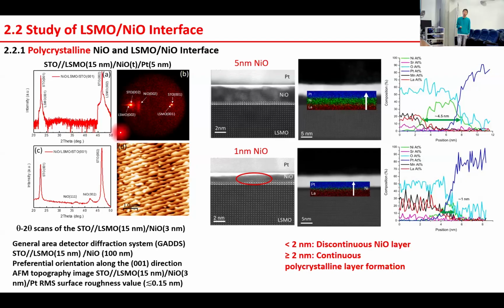With the 2D detection, we show the nickel oxide has a preferential orientation along 002. And also there's the integration curve, so there are both nickel oxide peaks, nickel oxide 111 and nickel oxide 002, indicating the polycrystalline structure of the nickel oxide. And also the device surface obtained from the AFM image shows a flattened surface as well.